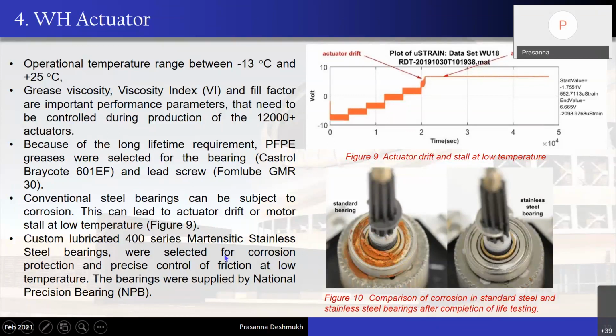In addition to this, we changed the conventional steel bearing. You can see here, this is a standard bearing which is available, and this is a stainless steel bearing, where you can't see any corrosion after the test. While designing the new actuators and testing them, we ensured that we are using commercially available components so as to keep the cost low. This particular bearing is very widely available from NPB. We use them.